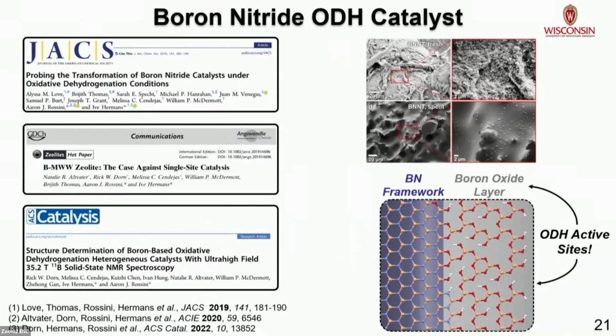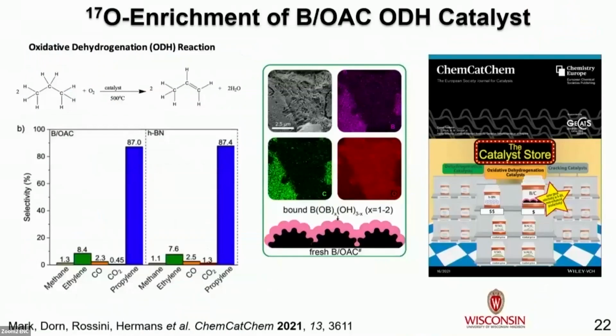So with this knowledge, we were able to recently rationally design and develop this new catalyst, which is boron supported on oxidized activated carbon, and it exhibits ultra-high boron weight loadings of about 28%. And what we see is that this boron on carbon catalyst exhibits almost identical selectivities to the new benchmark boron nitride catalyst, but it is more productive and overall cheaper to make.